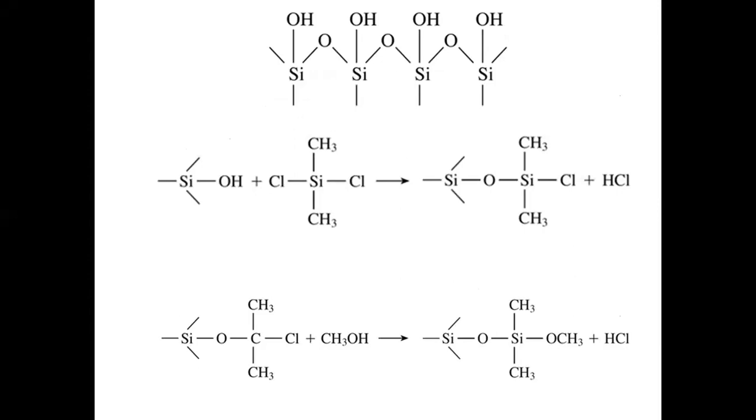Why is the unwanted adsorption going to occur there? If you see the first structure I have presented here, the unwanted adsorption is majorly due to the presence of OH groups here. So what do you call these OH groups? Silanol groups. These silanol groups will become the functional groups for the unwanted physical adsorption process to take place by the solutes. So these groups must be destroyed.